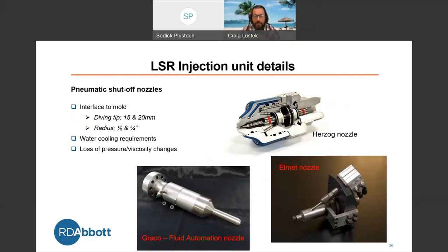Your pneumatic shutoff nozzles. These are mounted to the end of your screw and barrel, and this is that interface to your mold. We've got different company setups here. As you can see, the difference between the three that I have here, we've got radius and diving nozzle. Diving nozzles work more for your valve gate or open tip technologies versus your radius. That's more towards, let's say, a hot runner. There are water requirements for them, not always for a cold runner setup. You always need cold water though, the chilled water for your hot runner setup, as we don't want to cure that nozzle. That is your interface to that hot mold.